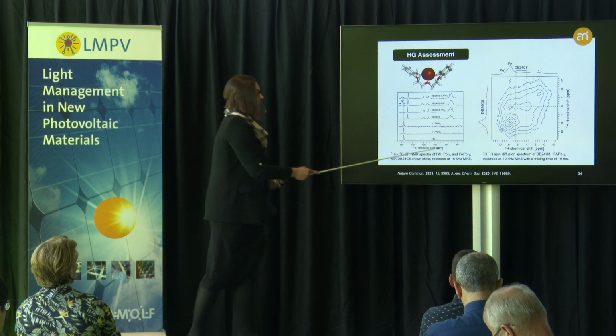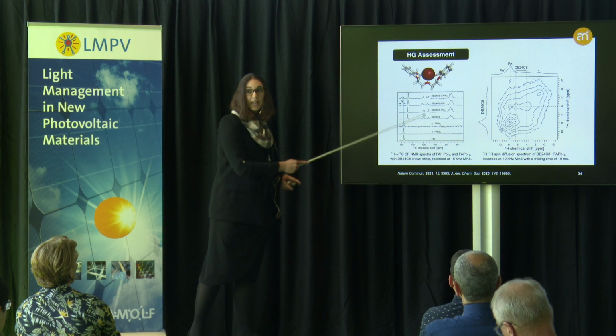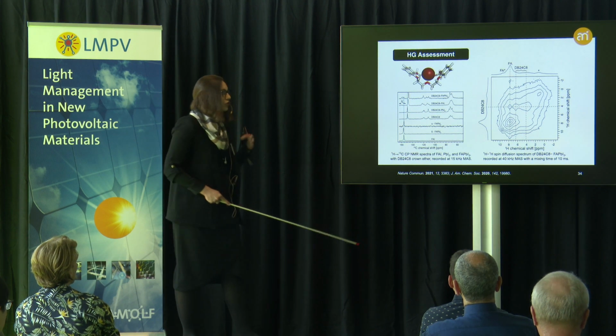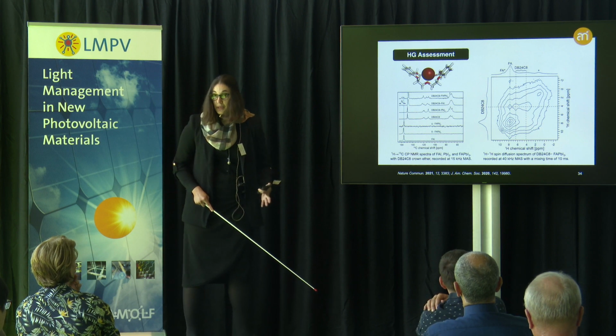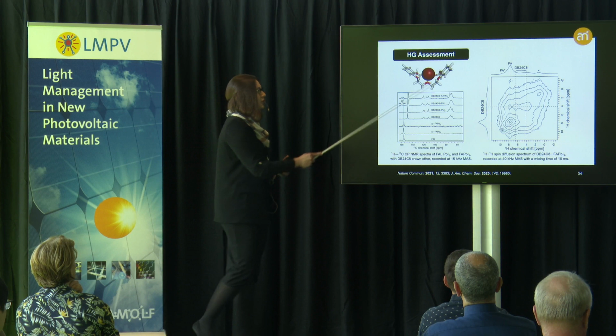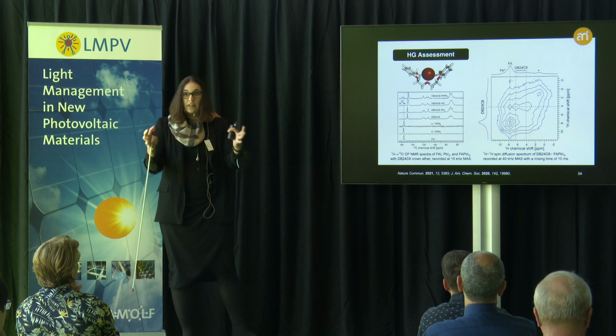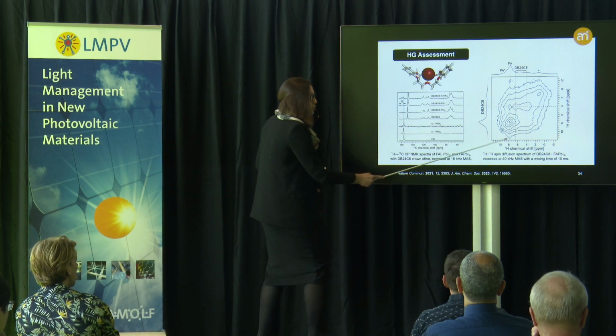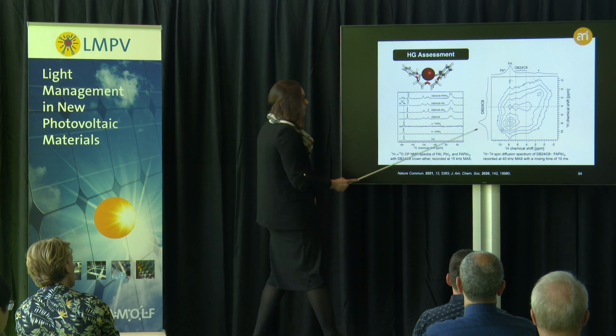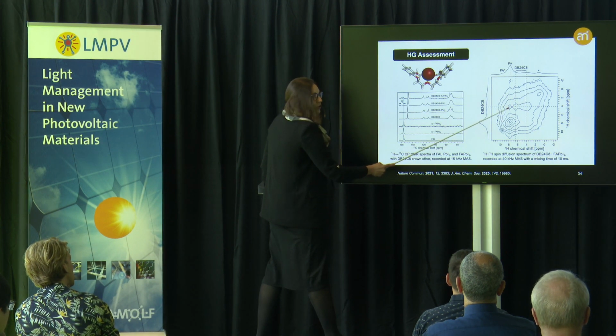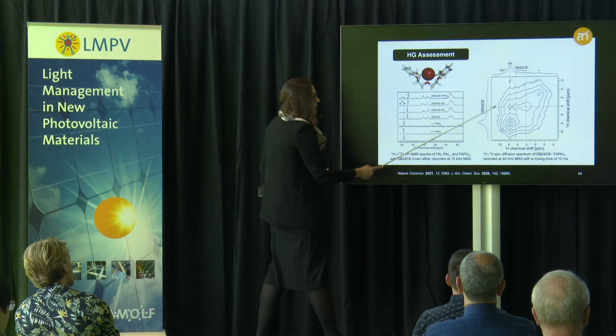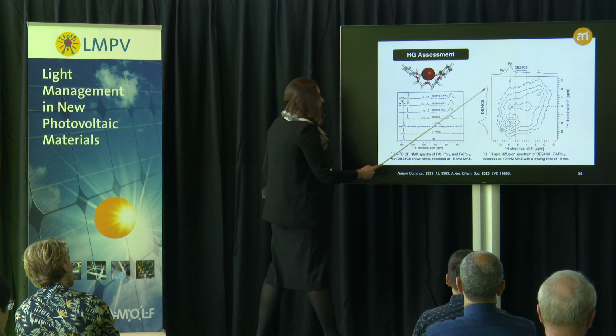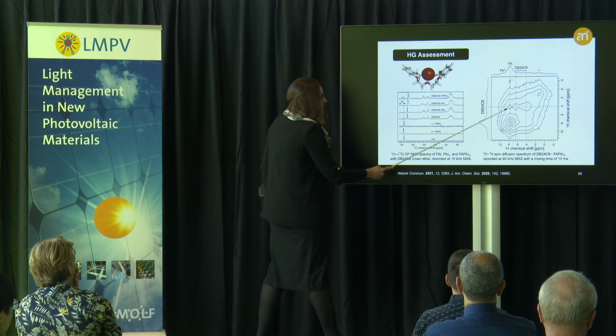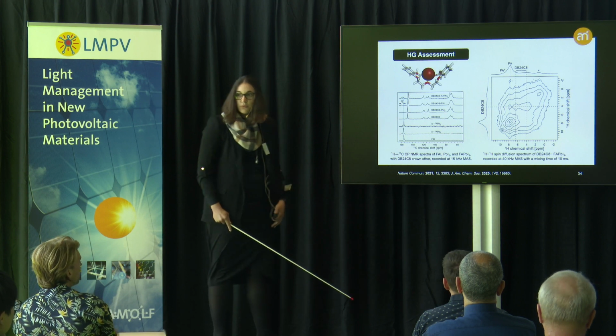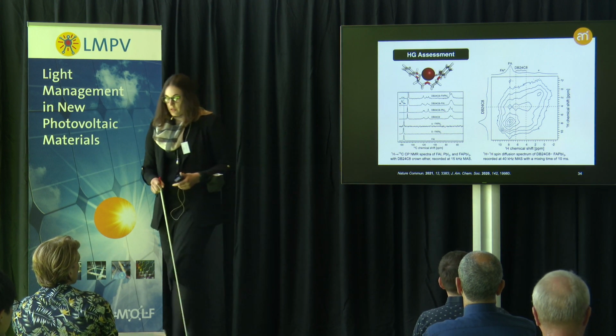Now, in order to really build confidence, apart from identifying these new environments and comparing these different NMR spectra, we can also perform two-dimensional NMR spectroscopy analysis, which essentially refers to monitoring the exchanges through space between two nuclei that result in exchanges in magnetization that manifest in these two-dimensional NMR spectra, in this case proton-to-proton spin diffusion experiments. They manifest in the formation of these off-diagonal signals that essentially correlate these chemical environments of the species, in this case the A cation and the host moiety, suggesting their presence in nanoscale proximity within the same phase, which offers us the confidence of the presence of this interaction.